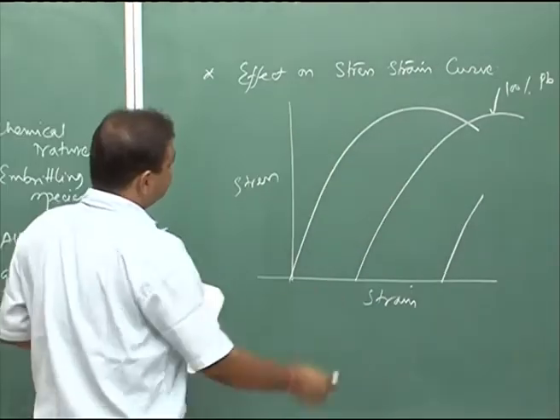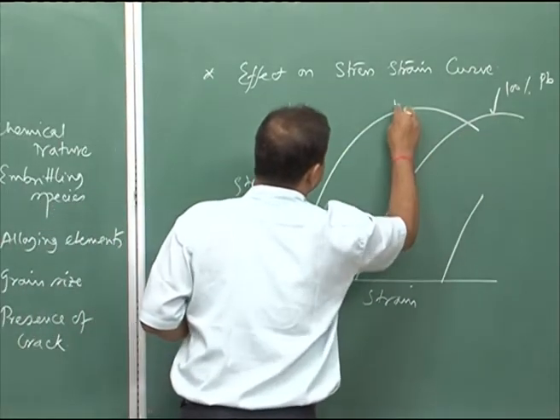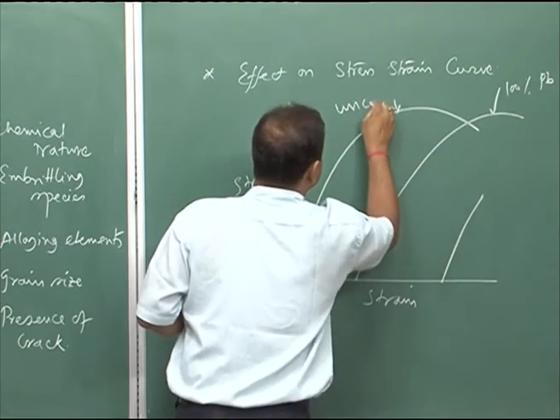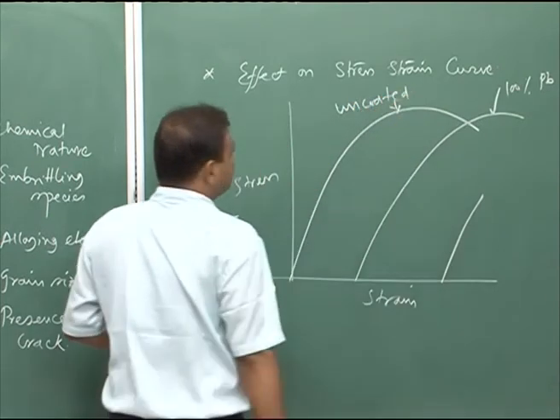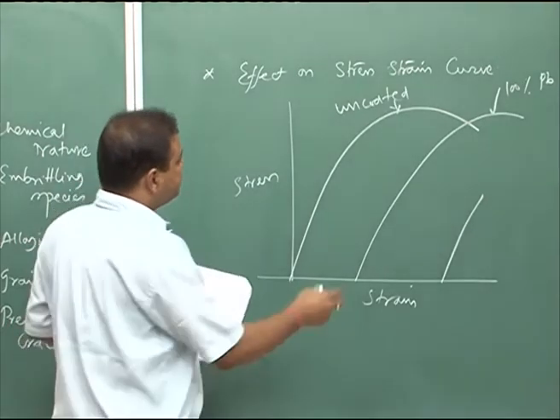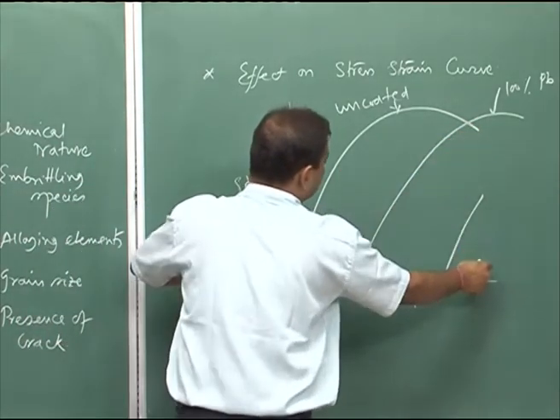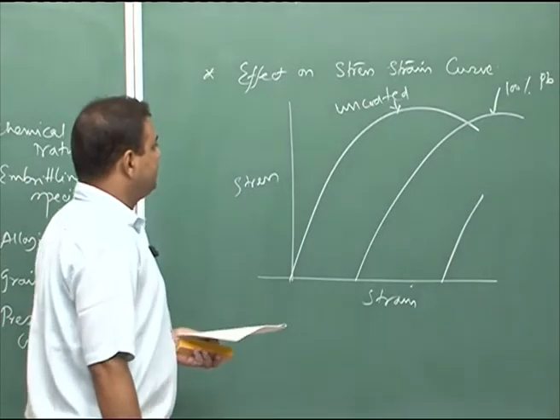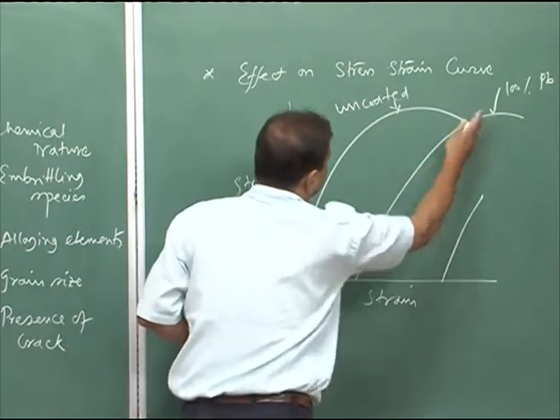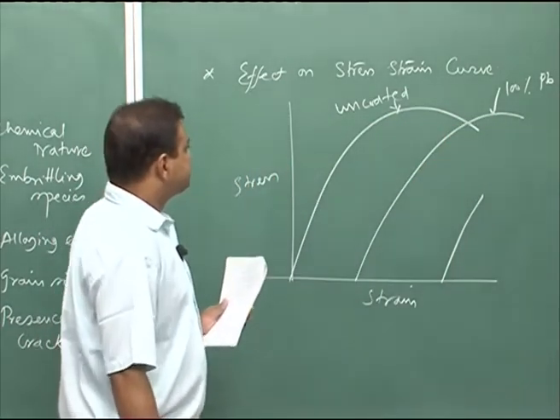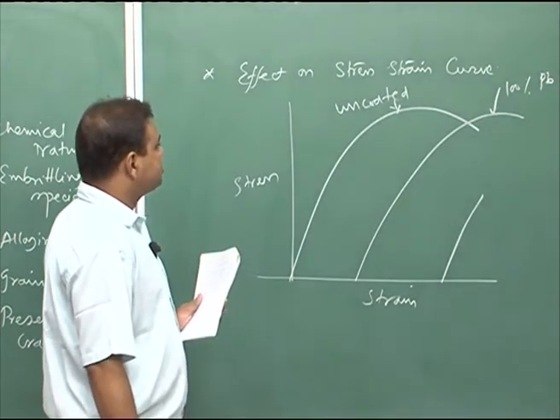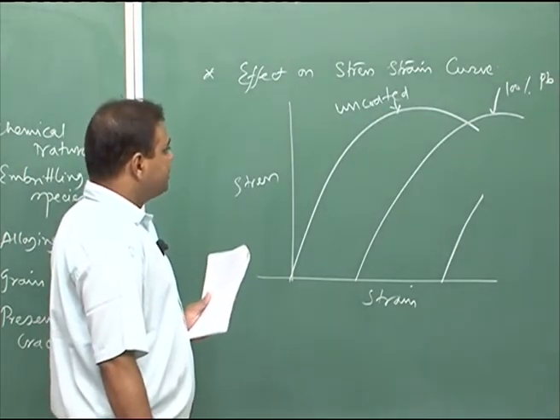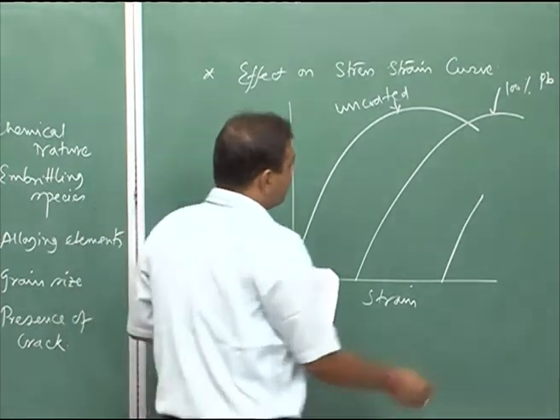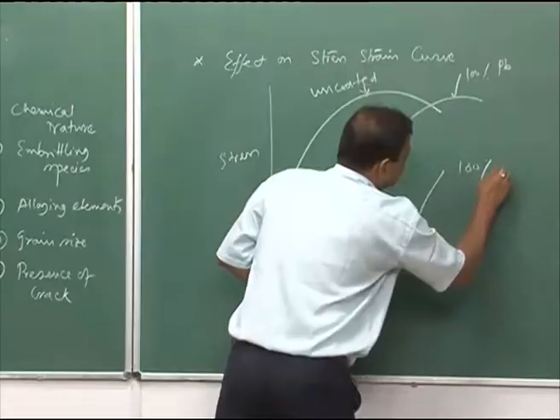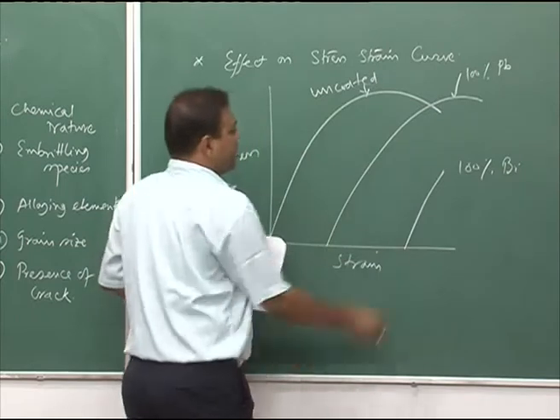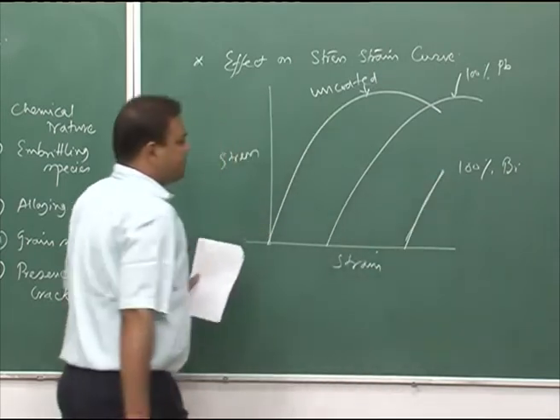So, you see in case of when it is 100% lead and this is uncoated, you do not have much change, but the only thing is there is a little decrease in the total fracture strain, but your yield point as well as ultimate tensile strength, those two things remain unchanged. But once we have 100% bismuth, you have a very aggravated embrittlement effect,